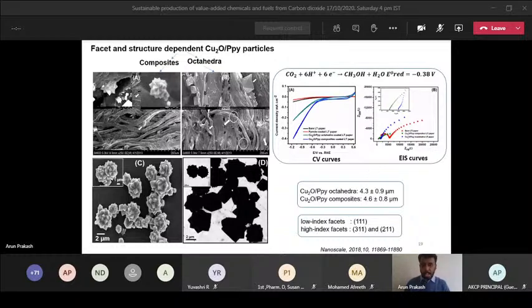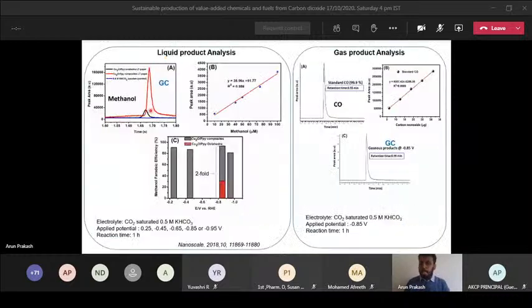In our case, we analyze the product after applying that potential. Here you can observe the potential which we apply, like minus 0.45 to minus 0.95, and depending on the potential applied, you can tune the Faraday efficiency. And this is the GC graph, gas chromatogram.